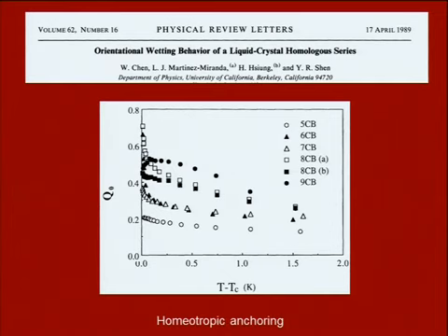The geometry that they usually look at is between two parallel plates, and they start from the isotropic phase, and they see how the amount of order, how the number of layers of ordered fluid, of nematic, depends on the temperature, the nematic-isotropic temperature. Okay, and for example, this is one of the papers. I'm only going to show you one or two. And this is fit, in fact, in the paper. If you look at it, it's fit by a Landau theory, and the authors claim it's in very good agreement with Landau theory. So for most of these liquid crystals, they all wet except 5CB, which is a little bit funny. 5CB is the one below here.